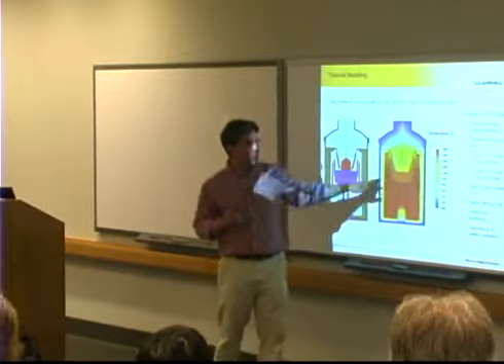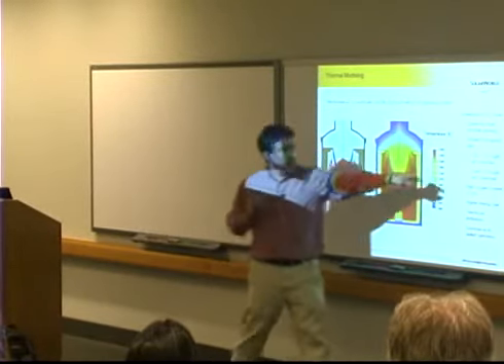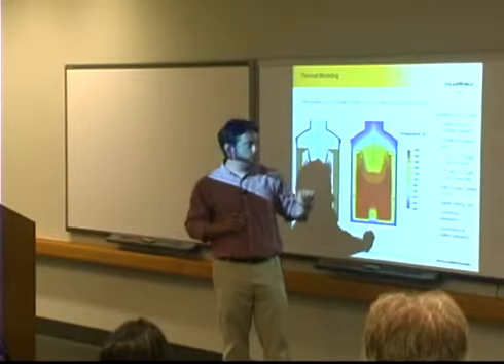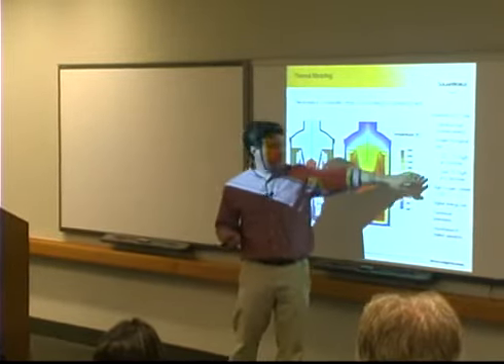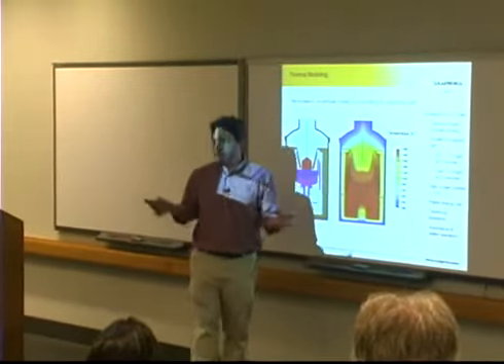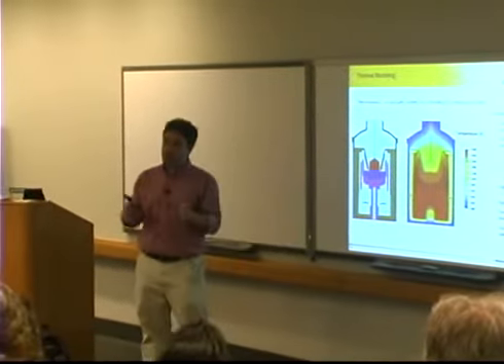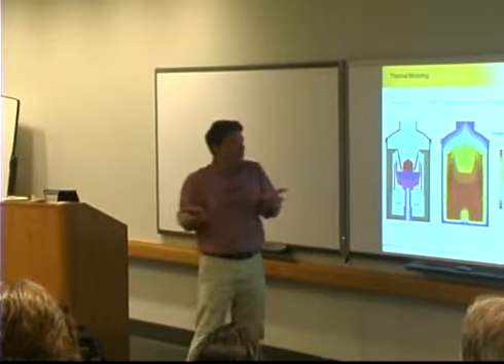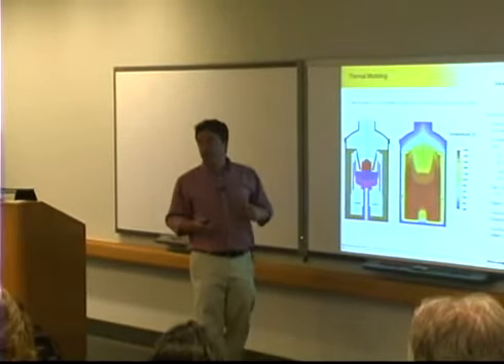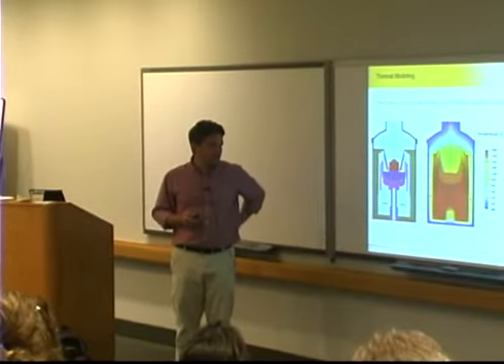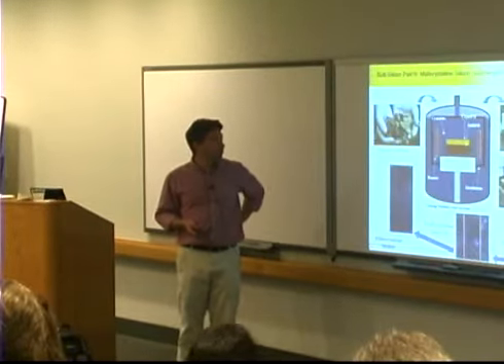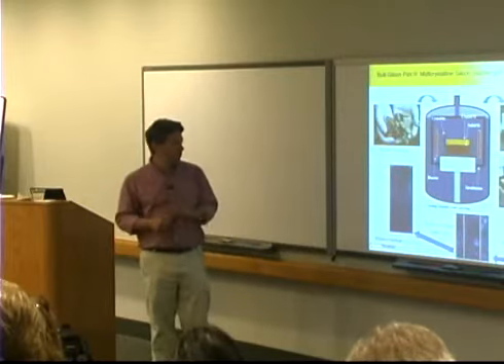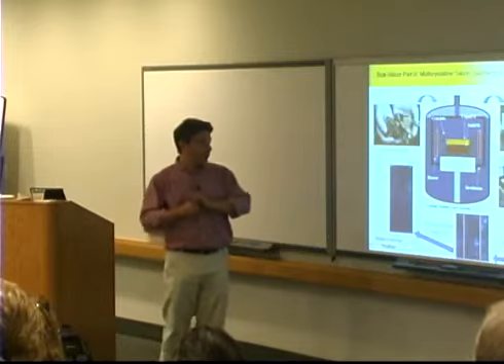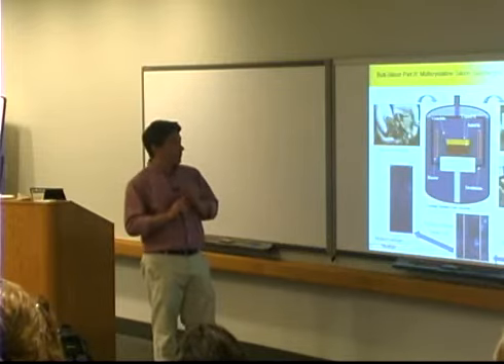So from a mass throughput point of view, the speed is relatively fast, but you're only getting 2.7 kilograms per hour. When I'm talking about the next process, multicrystalline, you can grow 25 to even 36 cross sections in one crystal. So as you're solidifying that interface, even though the linear rate is much slower, the area is much larger, and so you can get much higher throughput rates, which really cuts down on a lot of costs. Okay, so this is the last of the existing things, and then I'll get into some new stuff on the casting side, or on the bulk crystalline side.